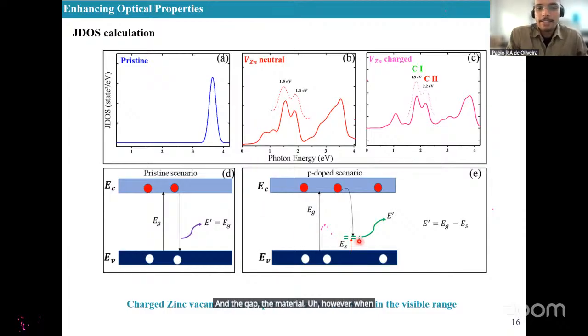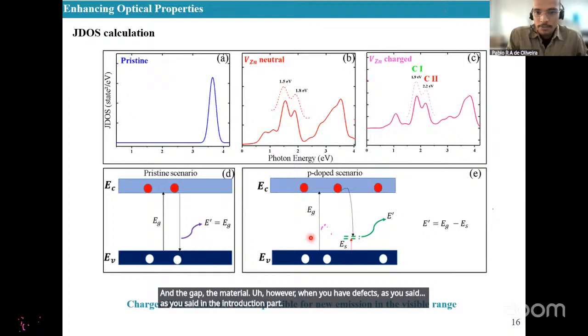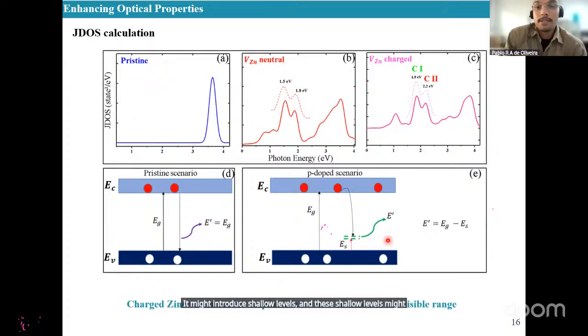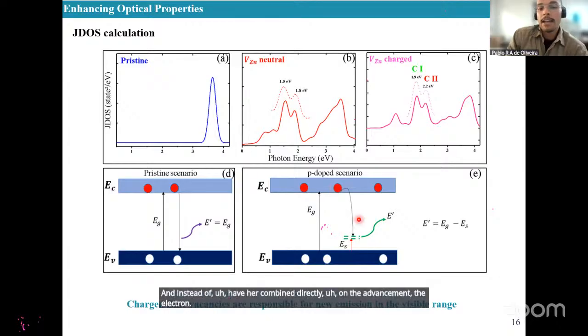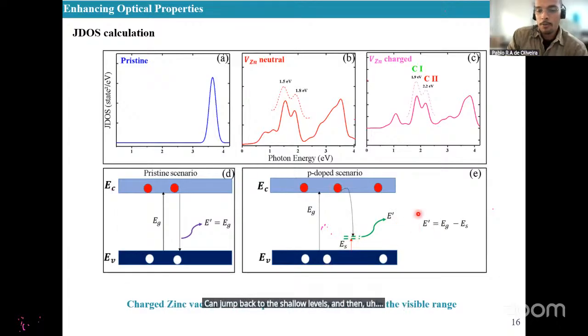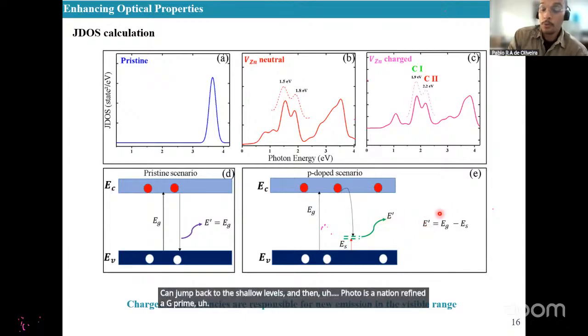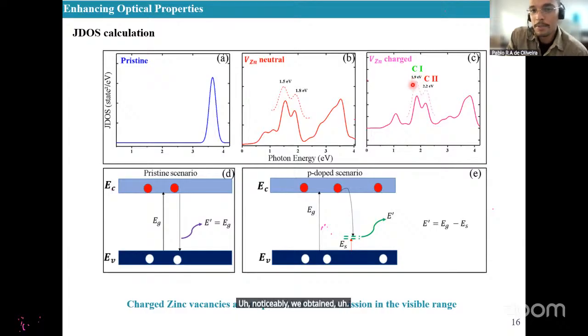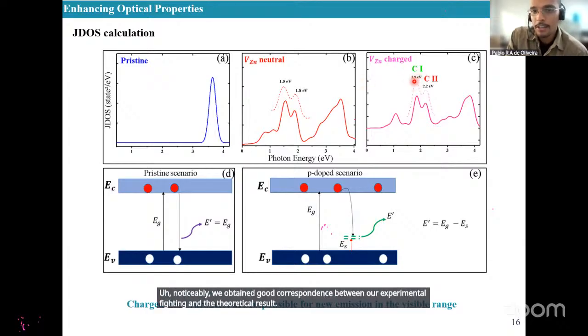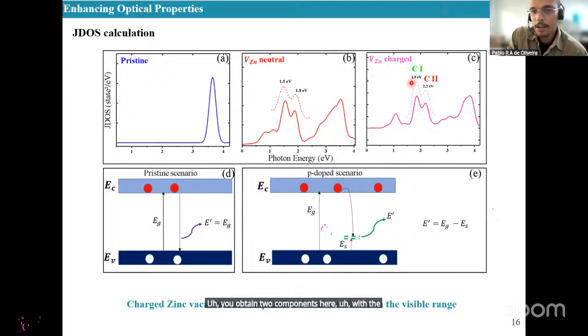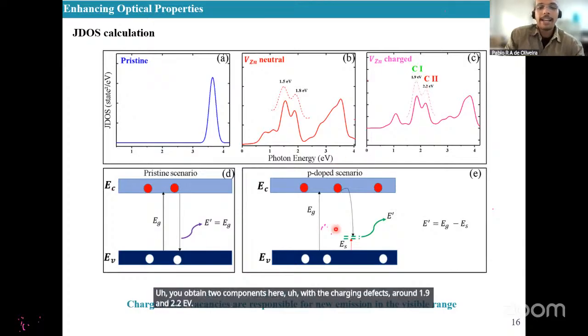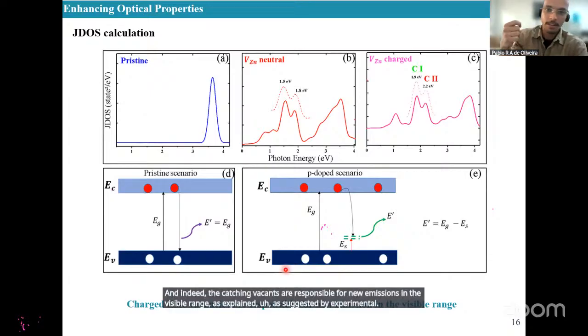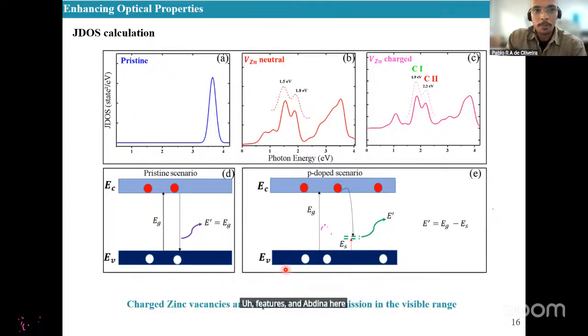However, when you have defects, as you said in the introduction part, they might introduce shallow levels, and these shallow levels might act as recombination centers. Instead of recombining directly to the valence band, the electron can jump back to the shallow levels, and then a photon is emitted with energy E prime, which is the difference between the gap and these shallow levels. Noticeably, we obtained good correspondence between our experimental findings and the theoretical results. We obtained two components here with the charged zinc defects around 1.9 and 2.2 eV. And indeed, the cation vacancies are responsible for new emission in the visible range, as suggested by the experimental features and obtained here from the theoretical point of view.